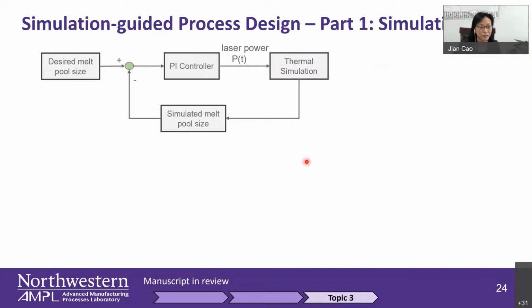Here in this case, we look at the laser power. One way, as I showed you earlier, that people have been doing is to look at the melt pool from the top using an infrared camera and use the melt pool length, right, the size. But as we know, when you build up things, particularly looking at the microstructure, which I'm not going to go into the details of right here, the melt pool depth also matters. So from the simulation, you can get that kind of information, not from the IR camera experiments.